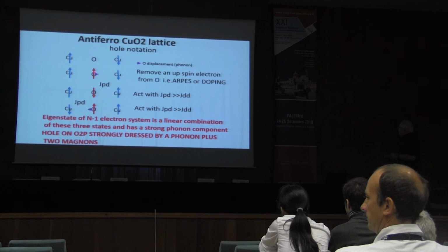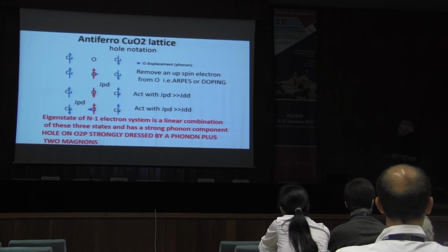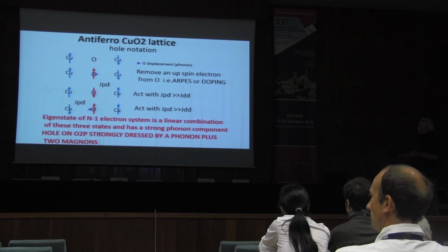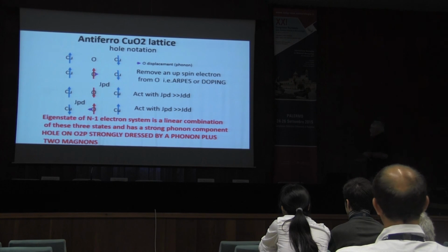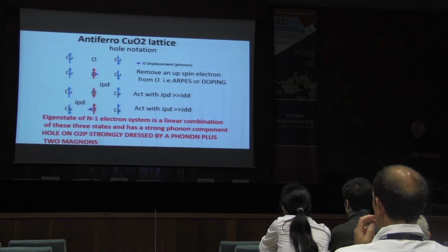So actually here, if you started out from this, then you see that from the Heisenberg exchange Hamiltonian, you can have this spin flip down and this spin flip up, right? So that's the other term that you would get, mixed in very strongly because of that very strong exchange interaction. Now, when you're over here, this oxygen is in an inversion symmetry, okay? So it doesn't have a preference, it'll stay in the middle. But now you go to this one, where this spin has flipped back up, but that spin has flipped down, and then the oxygen wants to move that way, because this is a very favorable state. So this is an eigenstate of an n-1 electron system, a linear combination of these 3 states. Now, it's not quite like that because you are in an antiferromagnetic background, but it's pretty close to that. And it has a strong phonon component, a hole, an oxygen 2p, strongly dressed by a phonon plus 2 magnons. This is the state of a phonon plus 2 magnons dressing this hole.